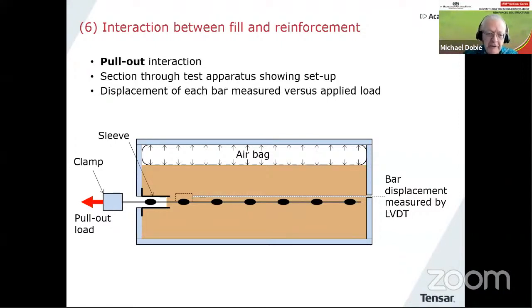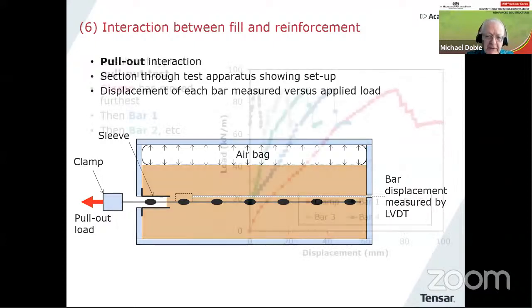And what you do, you're pulling towards the left, and you have the geogrid buried down there. Now, I'm talking in this case about geogrids which have fairly thick transverse members on them. And what we normally do then is we attach transducers to those to measure the movement of each individual part of the geogrid. And the kind of result we get from that would be something like this.